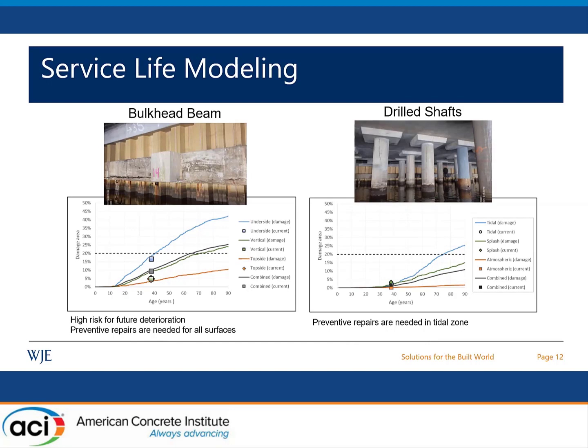So for the bulkhead beam, for example, we had enough information from the field investigation about the percentage of damage on each of the 3 beam faces, the underside, vertical, and top side. So we modeled those separately over the next 50 years, which puts us at an age of 90 years. And as you can see, the damage is expected to increase on all surfaces with time. And the model actually showed close correlation to the amount of damage that we observed in the field, which verified our modeling results. And based on the results, we identified high risk for corrosion future deterioration, and we recommended preventive repairs that's needed for all the surfaces.